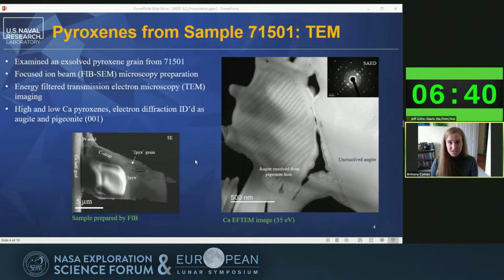We used energy-filtered TEM to visualize the exsolution lamellae. EFTEM is a parallel illumination technique in which only those electrons that have lost a characteristic amount of energy are used to generate the final image. So when we center an energy selecting slit on a characteristic calcium excitation feature, this yields the image you see here. The more calcium-rich phases are brighter. And then performing electron diffraction allowed us to identify these two phases as pigeonite and 001 lamellae of augite. And you can see here next door is the unexsolved pyroxene grain, which was also an augite.